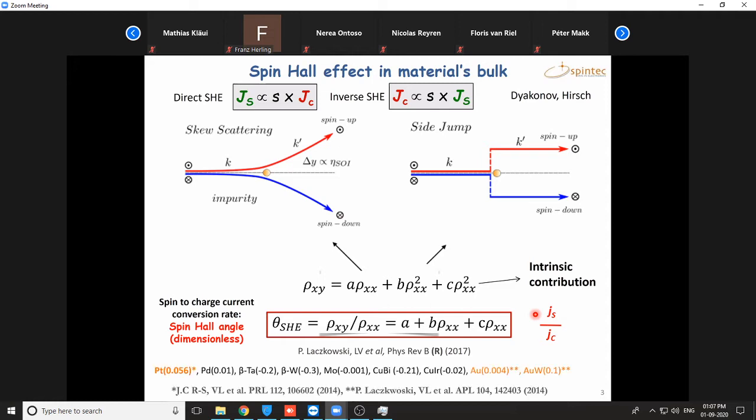So this has led to a very large amount of literature in the field. And there is some debate on the spin Hall angle of the material, even for a material as simple in a sense as platinum, or as studied as platinum, people do not yet agree on the spin Hall angle. One thing I would like to emphasize is that it is not only the spin Hall angle that is a key parameter, but also the resistivity and, associated to that, the spin diffusion length.